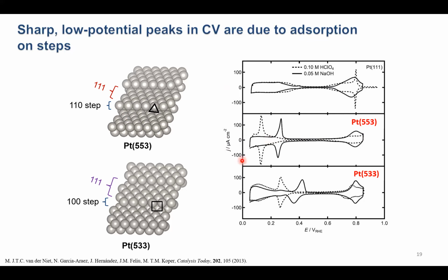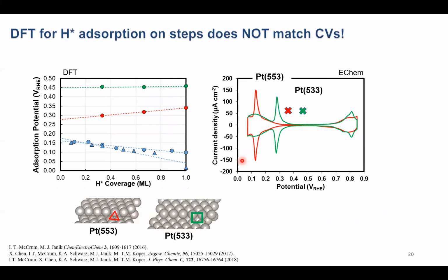We know exactly the geometry of our surface. And so first, because these step peaks were assumed to involve hydrogen adsorption, that was the first thing we looked at with DFT, right? We calculated the adsorption potential for hydrogen onto the terraces of these two stepped platinum surfaces shown in blue here, as well as on the stepped edges shown in red and in green. I should say briefly, this is ignoring the effect of near surface solvation on the adsorption of this hydrogen. We'll come back to that in a few slides.